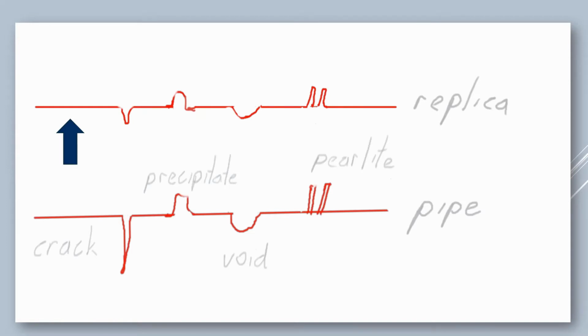And so you have to get used to looking at the reverse image of what you're seeing on the replica. The cameras will reverse it for you, but they don't seem to do a very good job of it. And this is an example of a cellulose acetate replica off a pipeline steel. They thought there was stress corrosion cracking, and so you're seeing all these lighter areas, those grains are ferrite. The darker areas are pearlite. Of course, we're not seeing any of the microstructure in the pearlite right now, the lamella, but that's a low enough magnification. So when they looked for stress corrosion cracking on the surface, there was nothing.